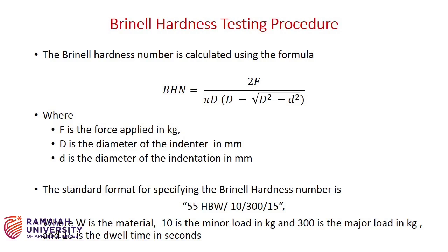The Brinell hardness number is calculated by using the formula BHN is equal to 2F divided by pi capital D times capital D minus square root of capital D square minus lowercase d square, where F is the force applied in kgs, capital D is the diameter of the indenter in millimeters, and the lowercase d is the diameter of the indentation expressed in millimeters. The standard format for specifying the Brinell hardness number is 55 HBW/10/300/15, where 10 kg is the minor load, 300 kg is the major load, and 15 is the dwell time in seconds.